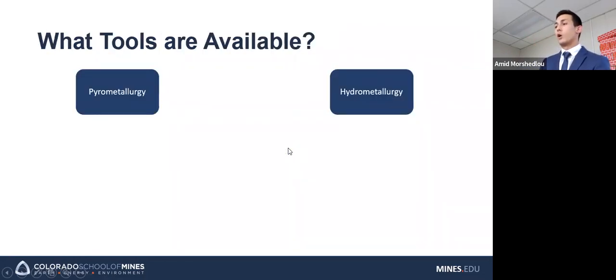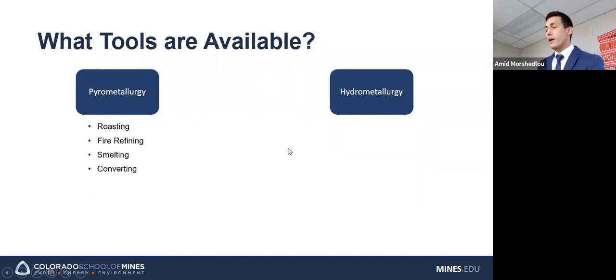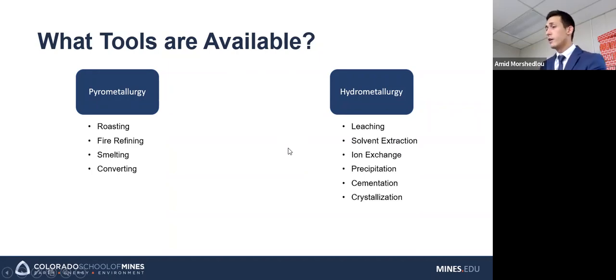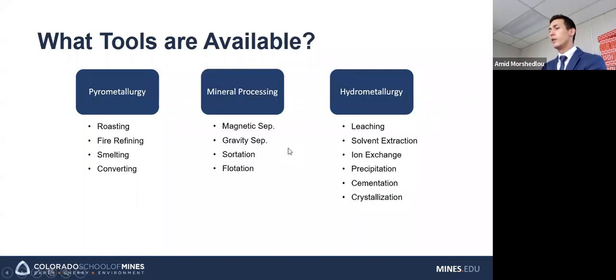How are we going to process this slag? Well, I've already talked about pyro and hydro. In pyro, there's roasting, fire refining, smelting, and converting, and smelting was what was used to generate this slag. On the hydro side, there's leaching, solvent extraction, ion exchange. We could do precipitation or some similar process like cementation. But regardless of which route we go with, we can also go with pre-concentration using mineral processing. That would likely involve some sort of flotation or maybe magnetic separation. These are the general categories, the tools we can use to process this material.